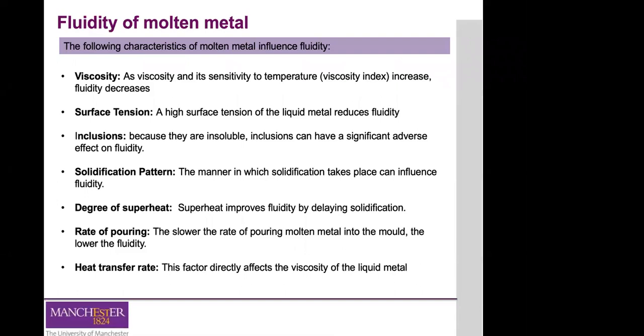The capability of the molten metal to fill the mould cavities is normally defined as fluidity, and this consists of two basic factors: the characteristics of the molten metal, and the casting parameters we use. The following characteristics of the molten metal influence fluidity. First, viscosity — as the viscosity and its sensitivity to temperature (the viscosity index) increases, we have more difficulty forcing the material to flow into the mould cavity. So fluidity will decrease with an increase in viscosity.